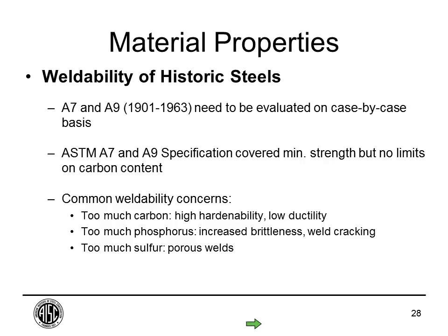So as I mentioned, most steels after 1963 are generally weldable. Before that, you need to evaluate it on a case-by-case basis. So historic steels that were in production before that, the ASTM specification covered the minimum strength, but they didn't provide limits for things like the carbon content, phosphorus, sulfur, and these are things that can cause problems with welding. If you have too much carbon, it can cause high hardenability and low ductility. If there's too much phosphorus, it can create increased brittleness in the steel and weld cracking. If there's too much sulfur, it can result in porous welds.